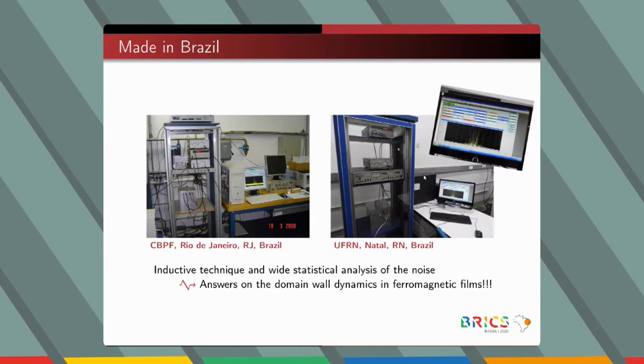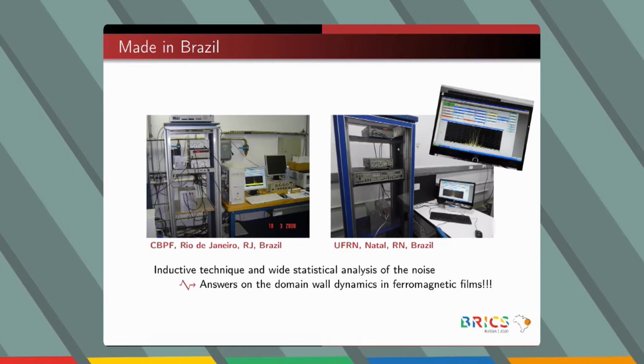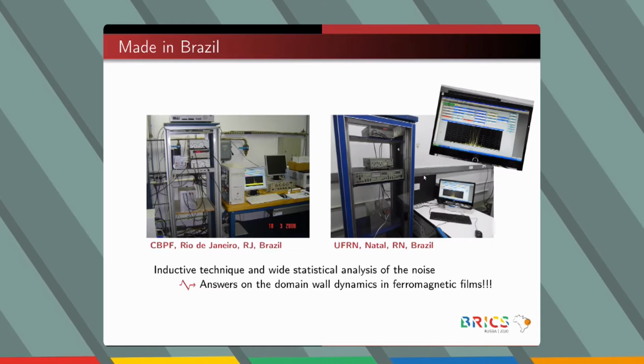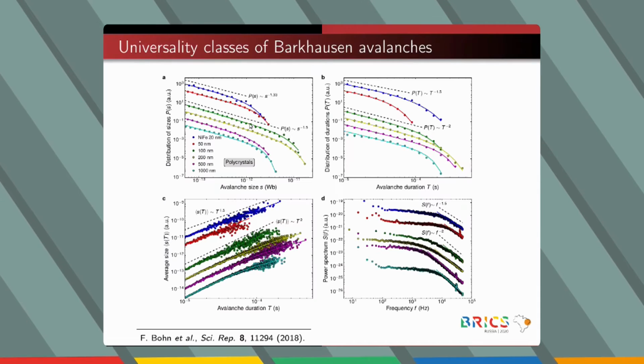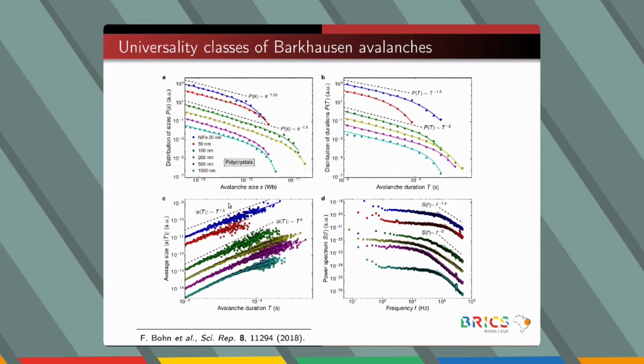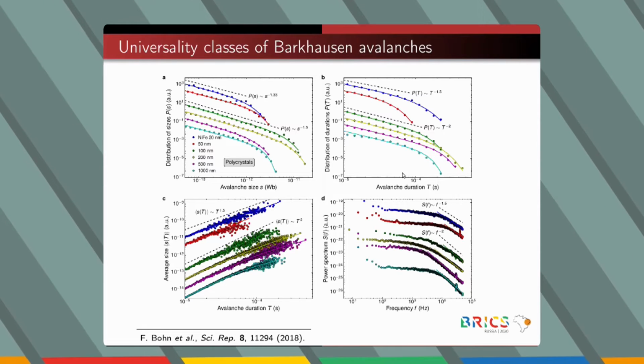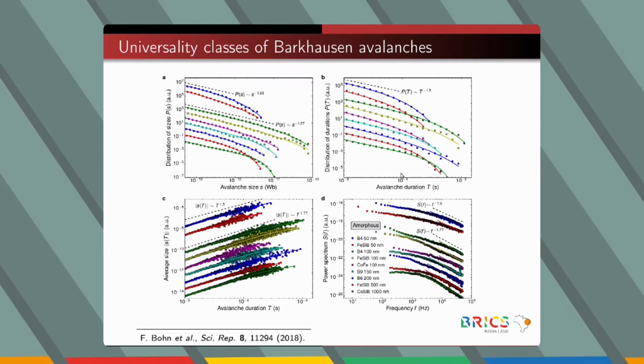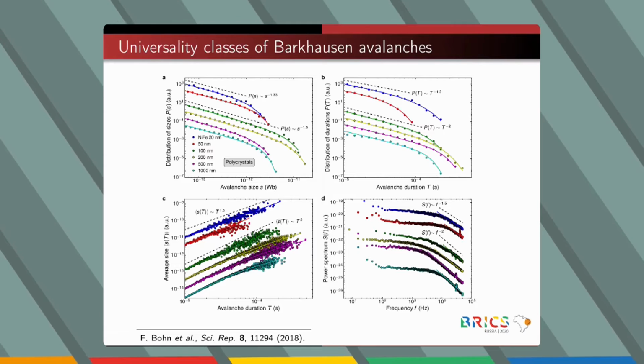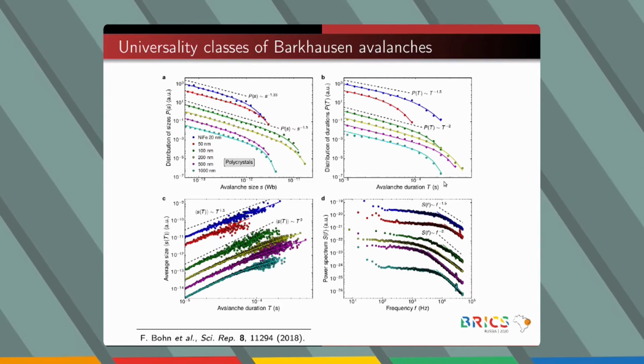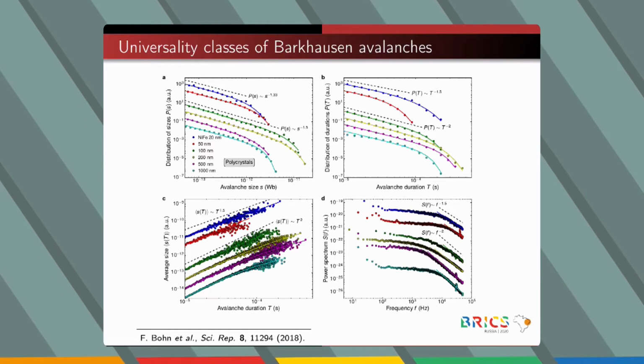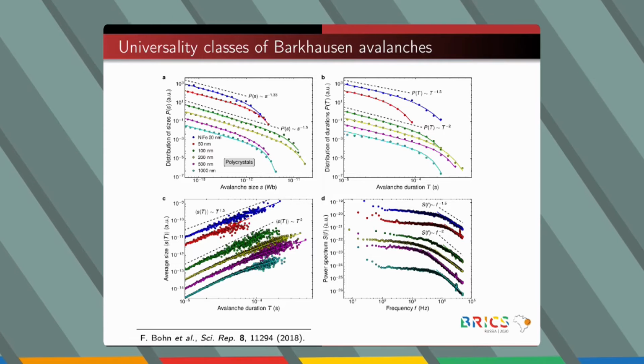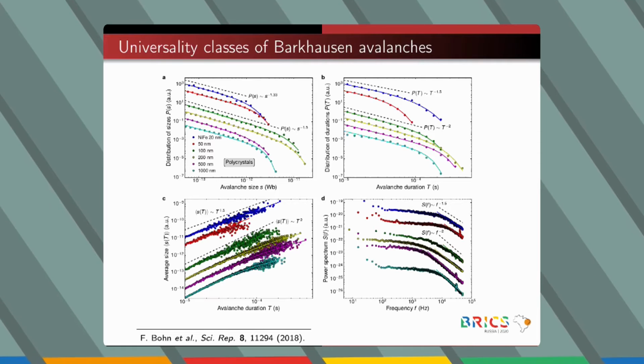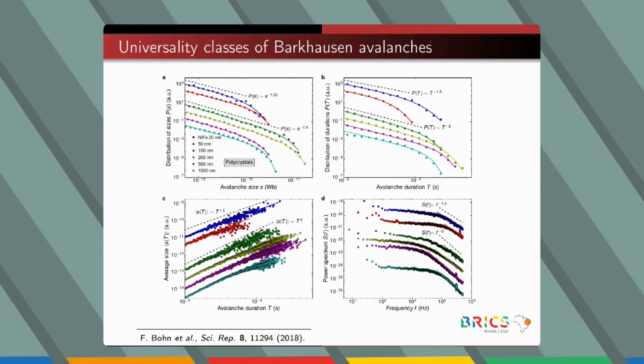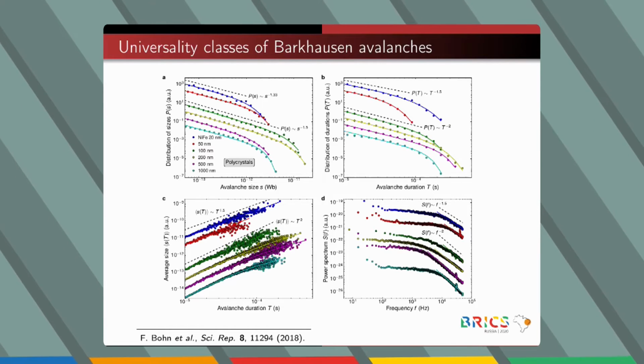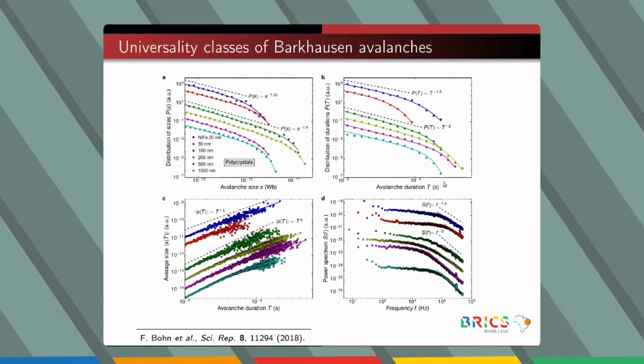Within this context, we performed a wide statistical analysis of the Barkhausen noise in ferromagnetic films, having variable thicknesses and different structural features. In this task, we consider the distributions of avalanche size, avalanche duration, the average size as a function of duration, and the power spectrum, each one described by an exponent. When considering polycrystalline films, they are divided into two groups according to the exponents, suggesting two types of behavior. By comparing experiment and theory, we interpret that films above 100 nanometers exhibit a three-dimensional magnetic behavior with long-range interactions, while films below 100 nanometers are two-dimensional with long-range interactions. Thus, we revealed a dimensional crossover associated to the type of domain walls.